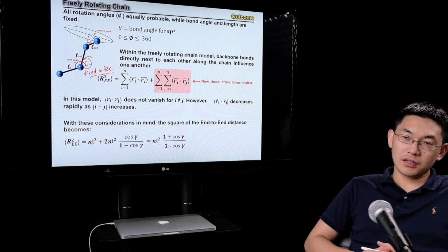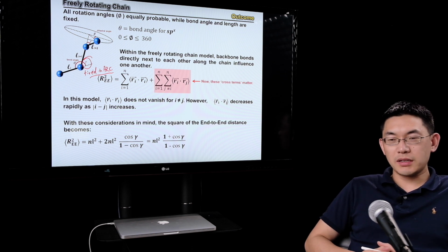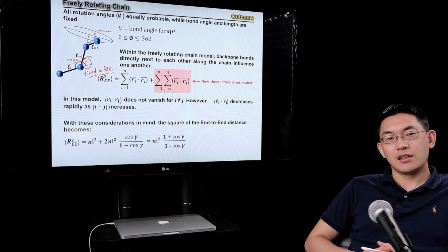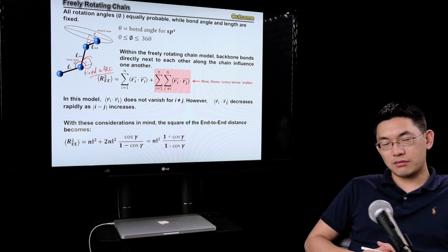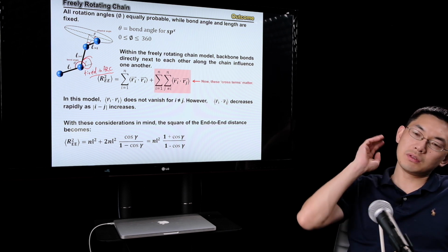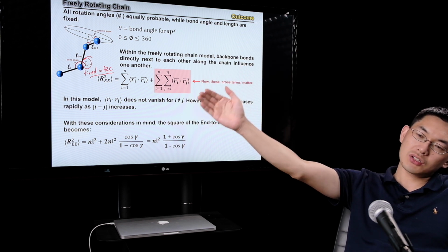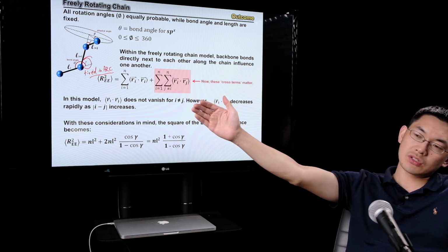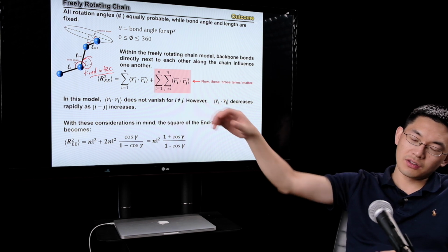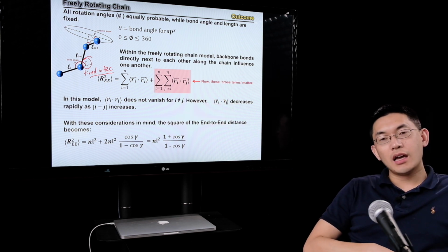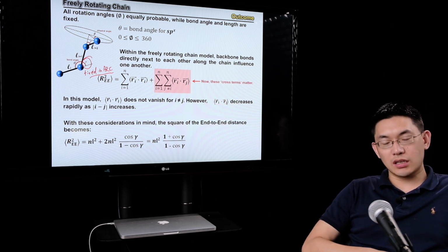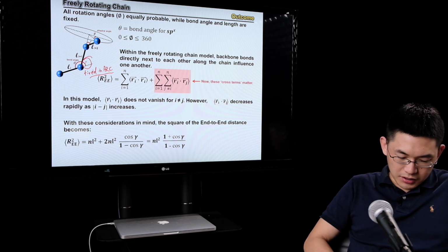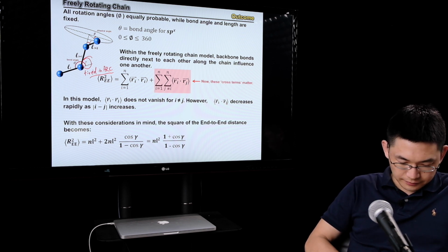But in short, I'm going to repeat the important finding 3 times. The fixing of the bond angle causes an increase in coil size. It is kind of understandable that if you fix the bond angle to be more directional, that would result in the chain going further along the backbone direction, right? And how much expansion there is can be simply calculated using the equation down below.